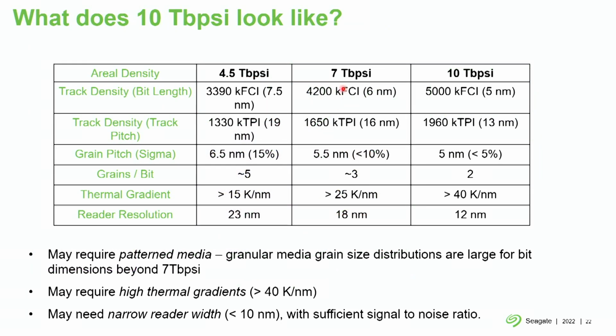I want to get to 10 terabit per square inch. What does 10 terabit per square inch look like? I mean, we modeled 4.5. If we wanted to double that, we're talking about 5 nanometer bit length, so 5 million BPI, 2 million tracks per inch, so 13 nanometer track pitch. Grain pitch has to be 5 nanometers because my bit length is 5. So my grains have to be at least 5 nanometers in diameter.